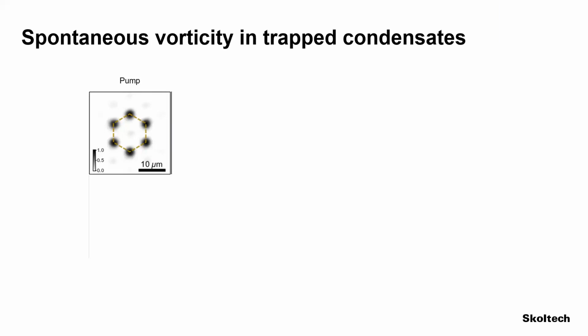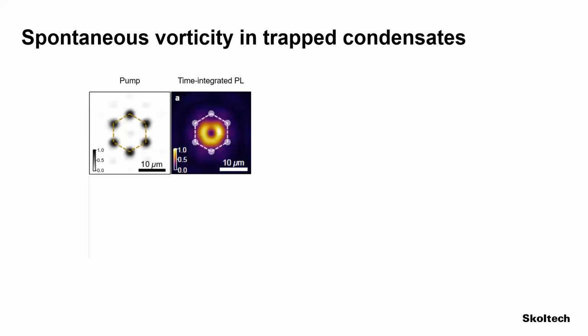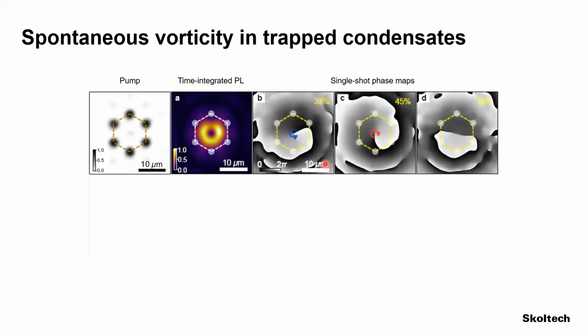So now, instead of creating the quantum vortex by rotating the bucket as I showed you before, I am pumping 6 spots in a geometry which allows the condensate to be formed in the center of the pumping spots. So that is like a loose bucket. A loose bucket has losses which practically drive a condensate to be formed here in the shape of a ring. Is that a quantum vortex? Well, if I do interferometry, I find that actually 37% of the times it goes anti-clockwise, 45% of the times it goes clockwise, and 18% of the times it forms a dipole state.